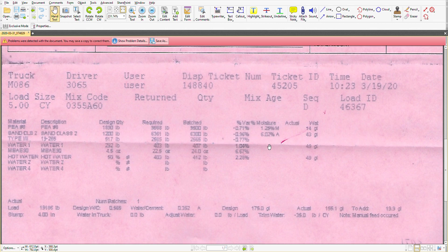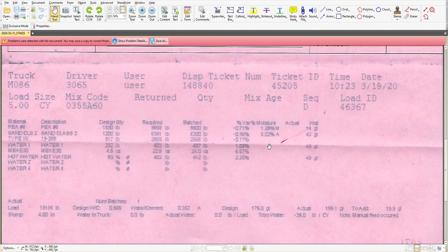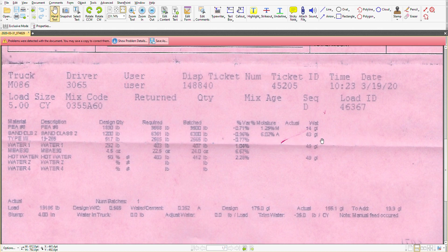So when it comes to the pea gravel, you'll see that they figured 1.29% of that for the moisture and the sand was 6.02%. Now here's where a little bit of math comes into play. Each gallon of water weighs 8.34 pounds. And so that's where some of this information has to be converted. Here we have our gallons of water.